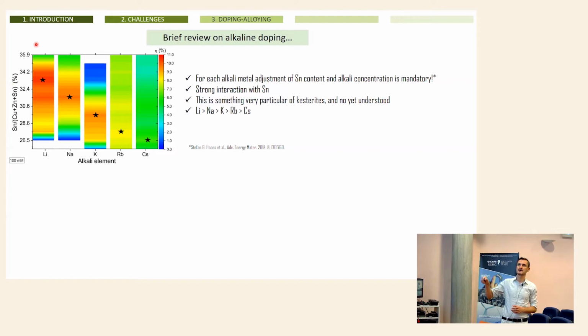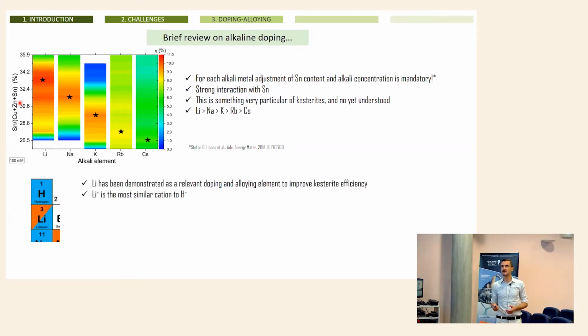So here you can have something like the tin concentration on kesterite, and here the different alkalines in different quantities. Then you can see that lithium achieved the maximum efficiency for 33% of tin. Nevertheless, sodium for 31, and potassium for 29, and rubidium for 27. Then, depending on the alkaline element you are using, the tin content to maximize your efficiency has to be tuned, and it's very different. And this explains why, depending on the condition you are working in, sodium is the best doping for you. If you are working at this tin concentration, potassium is the best for you. If you are working with this tin concentration, lithium is the best for you. This was a very nice discovery, and after that, lithium demonstrated to be the best one.